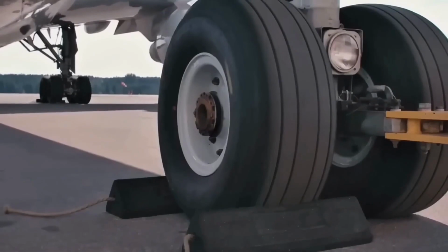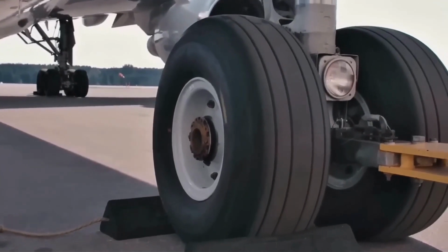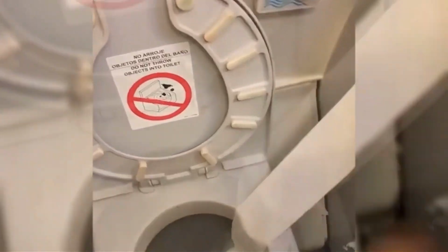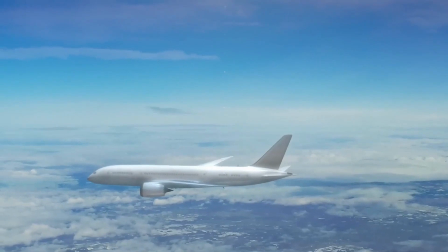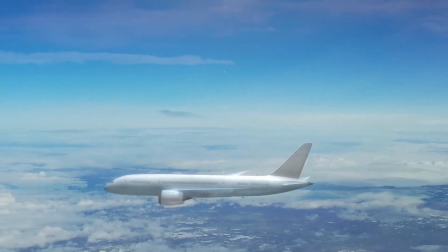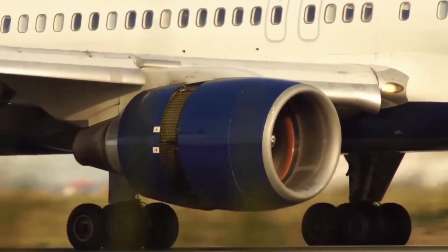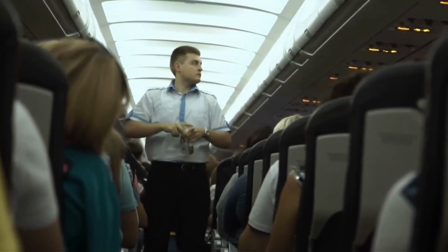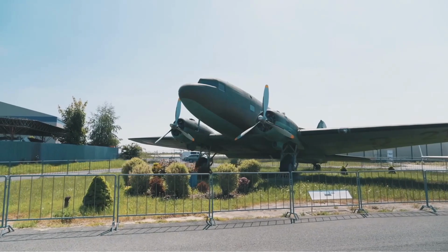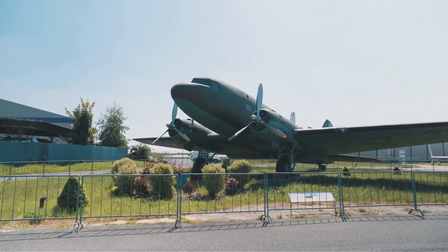Investigators from the Royal Aircraft Establishment eventually traced the failures back to metal fatigue that started at the corners of the window frames, exactly where stress concentrated most. That investigation reshaped how every pressurized aircraft has been designed ever since. It's the reason round windows aren't a stylistic choice. They're a direct engineering response to one of the deadliest lessons in aviation history.